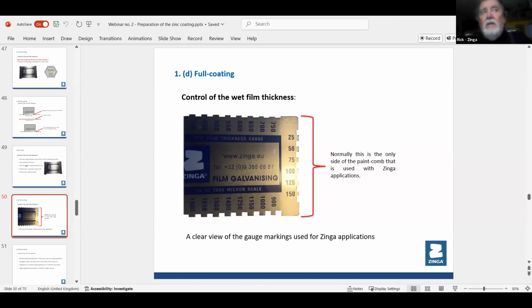Where a guy's putting on a top coat, okay, then you want 80 to 90 microns of Zinga, and then you're putting on a polyurethane or whatever. So then you apply 150, which is the highest point on that side. You would very, very seldom use the other 3 sides of that comb.